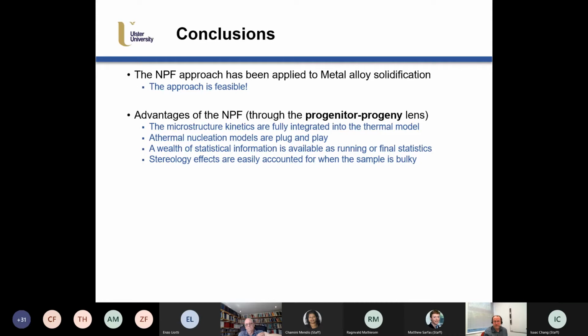But consider this: if you're doing this post-mortem, if you're doing a traditional polishing and etching of a sample, you have a different kind of stereology problem. You have a sectioning stereology problem. So your volume fraction and your area fraction will be kind of similar, but the average grain sizes will be smaller because you've taken a section, you've taken a cut through. That's assuming it's equiaxed, of course.